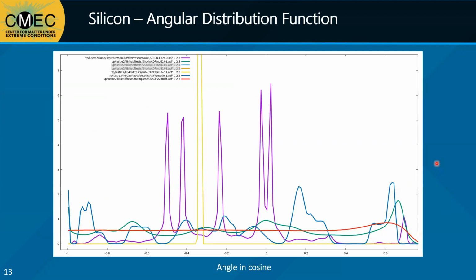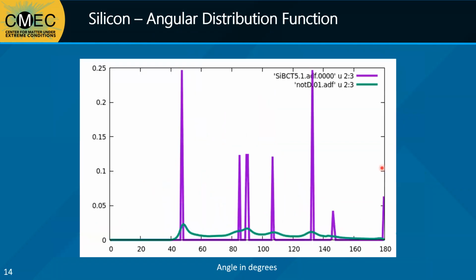We found that the most promising yet still relatively simple measurement for checking our structures against each other was using the angular distribution function. This calculates the angles between any three atoms in our simulation within a certain cutoff distance. Our shocked silicon sample can be seen as the green line here. We can see that none of these other curves quite match up perfectly, where they have different peaks or different valleys compared to the green sample. That is, of course, until we found our perfect match, which was BCT5.